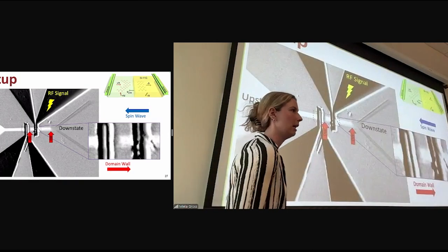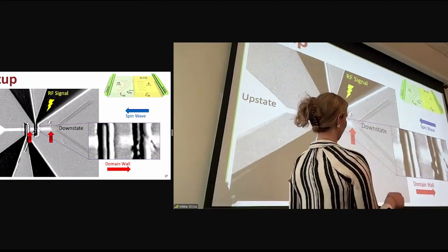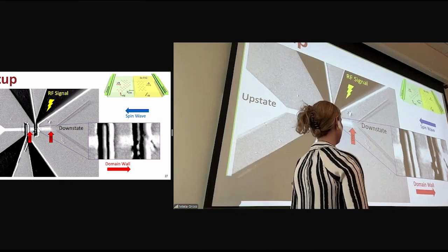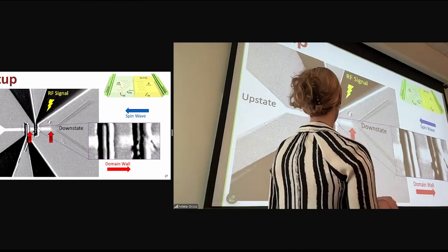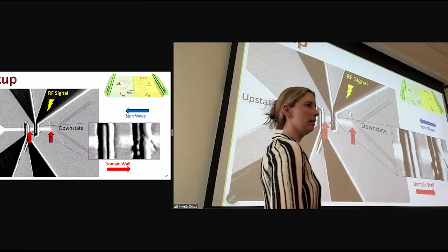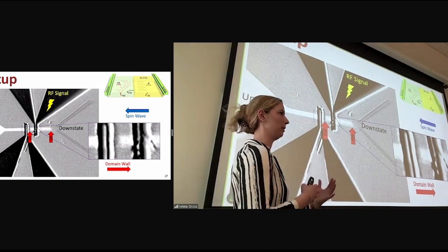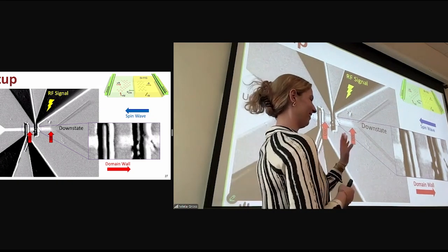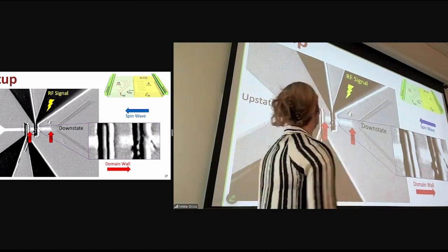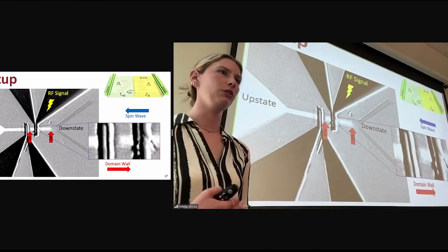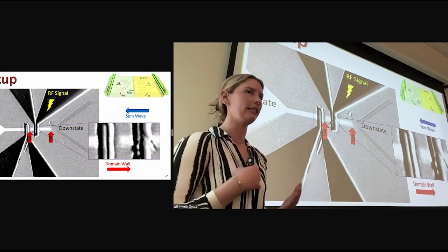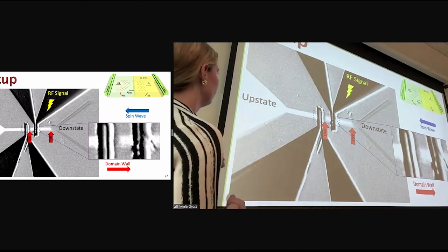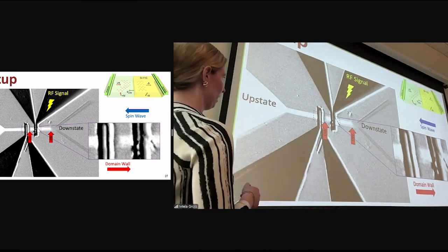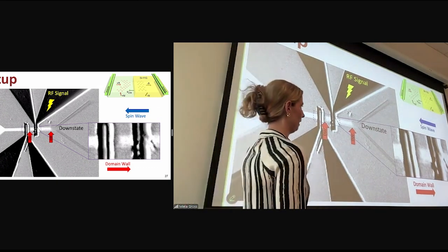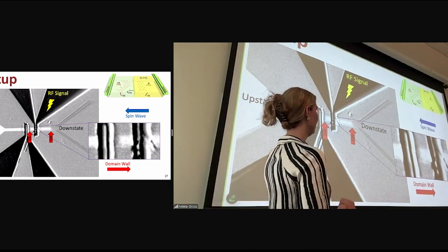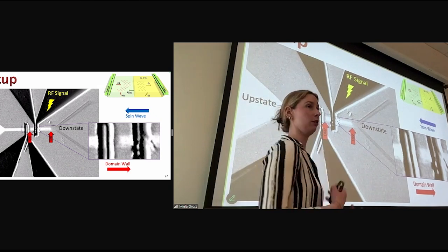So this brings us to the setup of our spin wave induced domain wall motion experiment. And I have our little animation in the corner to remind you guys what we're looking at. And you can kind of compare. This is our bismuth YIG racetrack. These are RF antennas. And this image was taken with MOKE. So it's a MOKE image. MOKE stands for magneto-optical Kerr effect. And what that does is it basically allows us to visualize the magnetization in very magneto-optically active materials like this bismuth YIG. So for example, that's how we can see that this bismuth YIG racetrack is nucleated in the up state here, and then the down state is in the dark region on the right here. The region between the up and the down states, these little areas here, are where the domain walls are present.